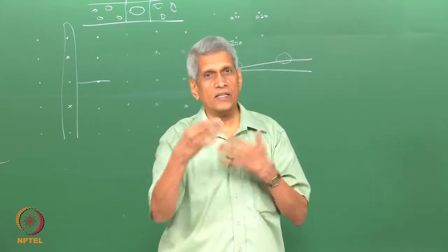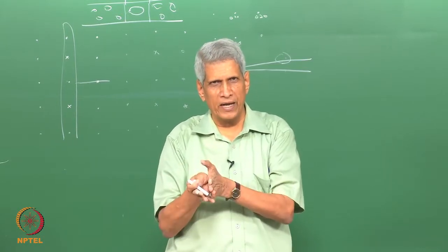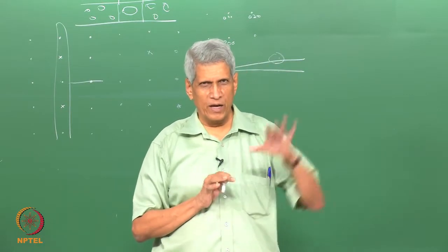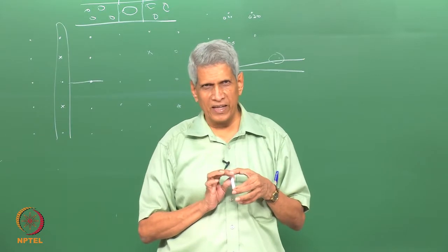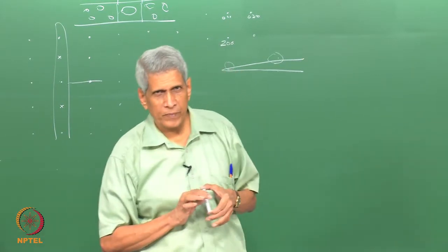So this is another way you can verify it. That is, if we suspect that there could be a double diffraction, you come close to the edge of the foil and try to look for a diffraction pattern. That way we can identify whether some spots are coming due to double diffraction or not. Is it clear?